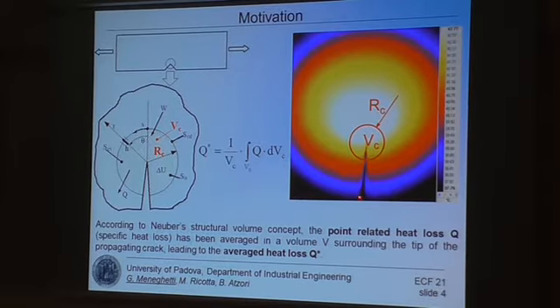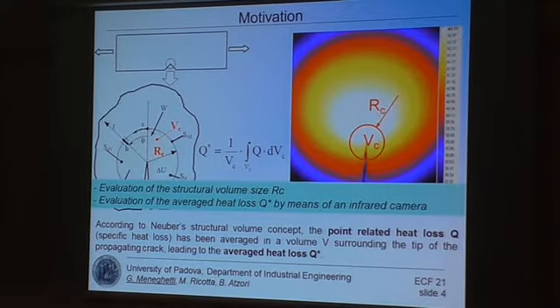Now, if we look at a sharp notch, this is a typical infrared image at a crack tip, really, in this case. The idea comes from Neuber's structural volume approach, where the fatigue damage index, in this case the heat energy, must be somehow averaged in a structural volume. So the fatigue damage index can be expressed like this. It is averaged in the structural volume size, and we have to integrate the energy dissipated inside the volume. So we have two terms to define in this model: the size of the structural volume, RC, and we have to evaluate the average heat loss Q by means of this integral.